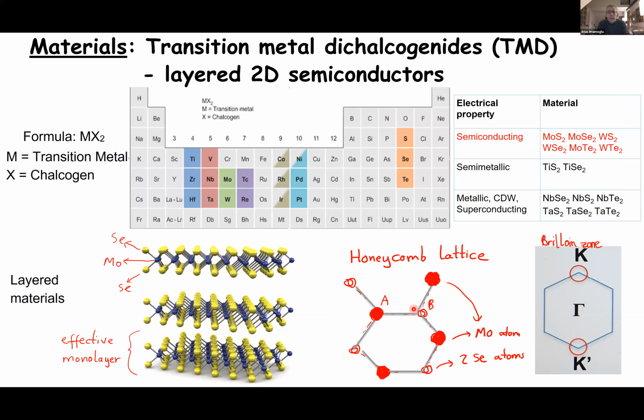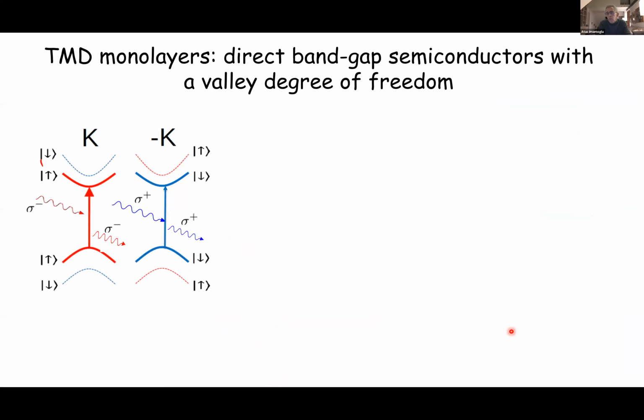This has similarity with graphene, but the sublattice symmetry is strongly broken, and this results in a large band gap at the high symmetry points K and K prime of the Brillouin zone. For monolayer TMDs, this band gap is direct. So this is fantastic. When we look at the optical properties, the optical excitations, we basically have this additional degree of freedom, which is the valley degree of freedom or valley pseudospin.